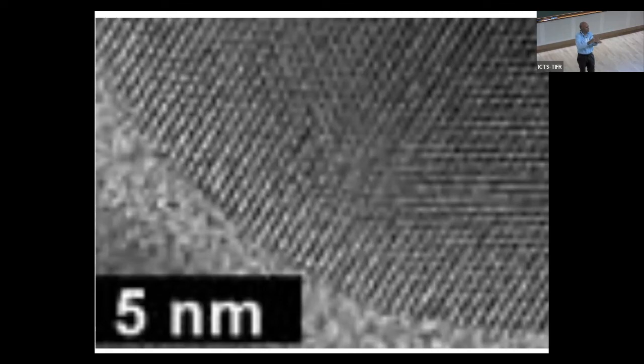So that's why, for example, in the famous mercury superconductor with 3 and 4 layers, the carrier density is optimal at the middle and lower on the top and bottom, and it suffers less frustration, and the TC has gone up to 160 Kelvin. And there was another experiment, somebody poured water in a cuprate, and the TC went up. Please don't laugh. It was an experimental fact, and somebody put alcohol also, TC went up. The physics is, in fact, a similar thing happened in the sodium cobalt oxide layered system with water, because the intercalated water offers high dielectric constant, and it reduces this charge order tendency. So they help suppress one of the competitors.